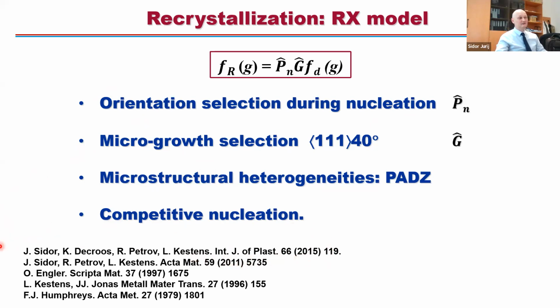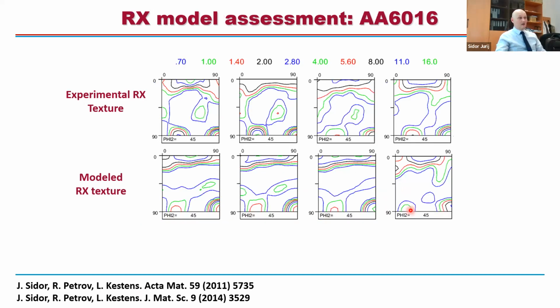Materialia, and so on. And our model was based on the previous models, which were developed by Engler, also Kestens, work of Kestens and Jonas. And regarding particles, we took the knowledge from the group of Humphreys. So when you have particles, then you have particle affected deformation zone, and then you have PSN, particle stimulated nucleation, which in fact competes with the bulk nucleation. Right, so how about a couple of words about the performance of these models.